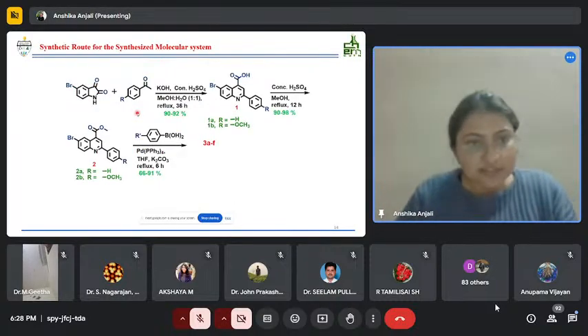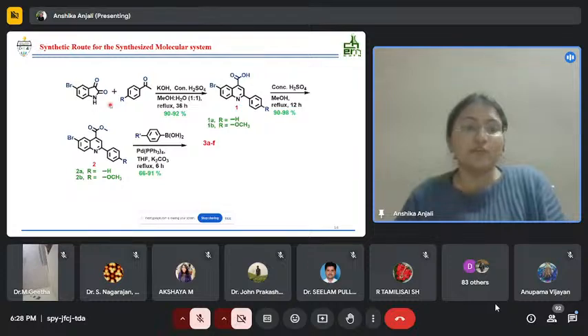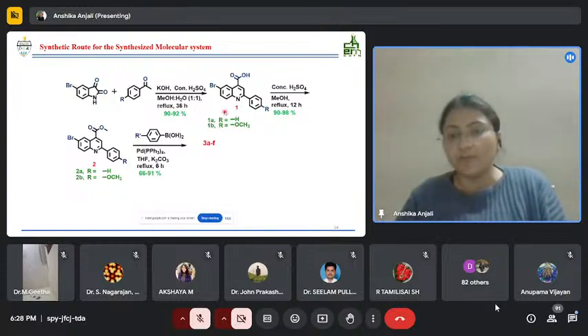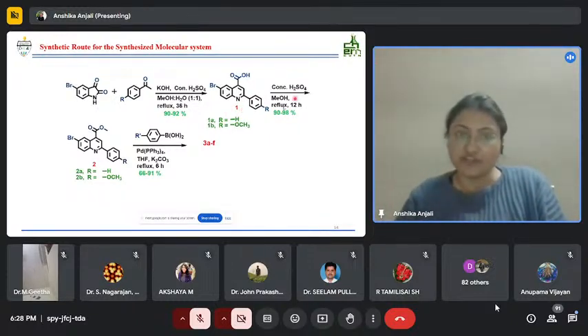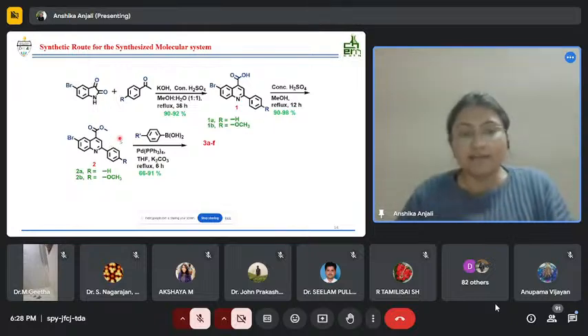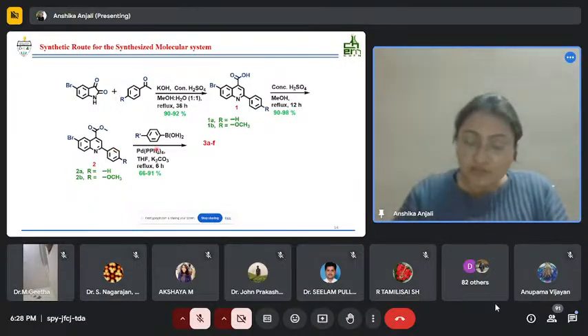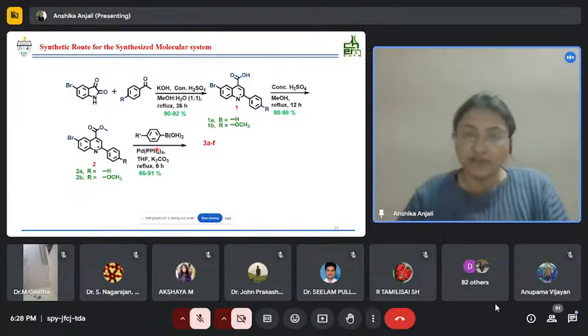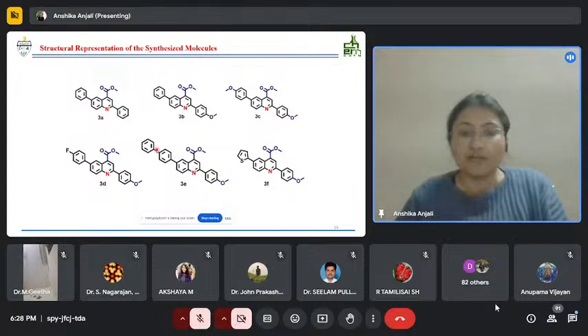So for the synthesis of these molecules, we have carried out the Pfitzinger reaction between 5-bromo isatin and substituted acetophenone in alkaline condition to give compound 1. Then compound 1 underwent esterification. The reason to do the esterification is just to improve the overall solubility of the compound. And this compound 2 then underwent Suzuki coupling reaction to give the final compounds in good yield. These are the final compounds that were synthesized.